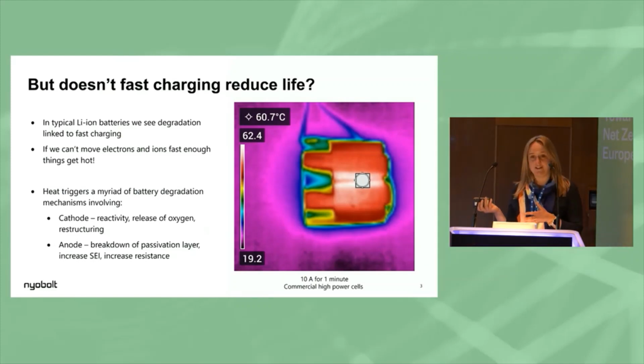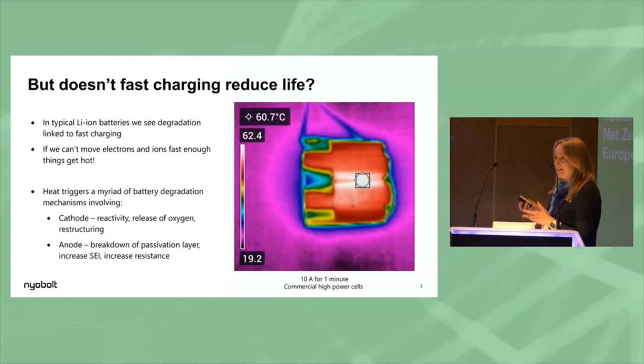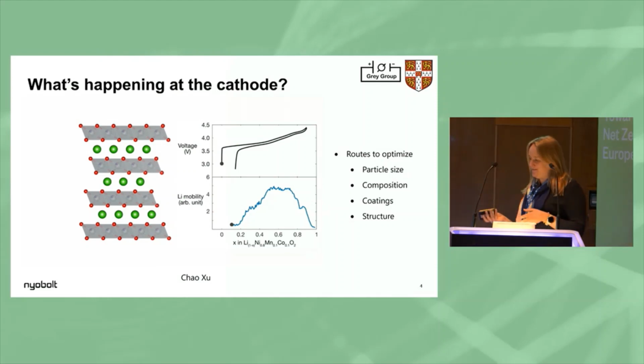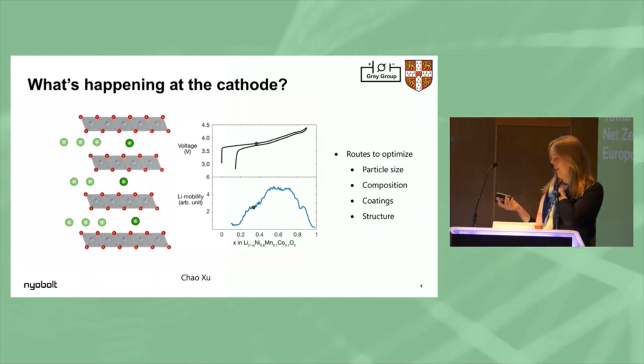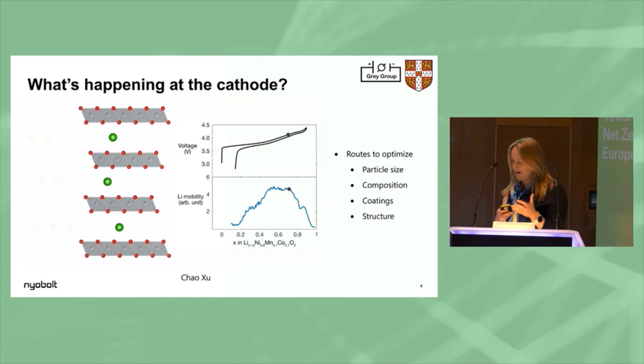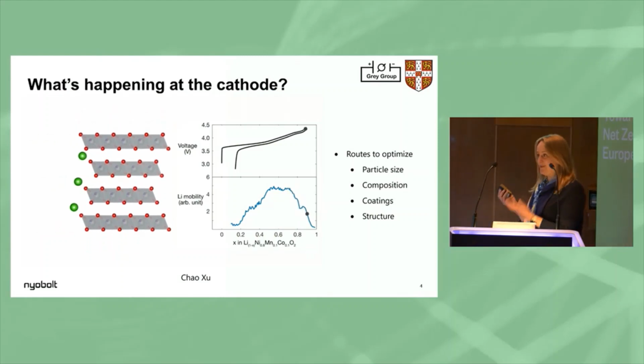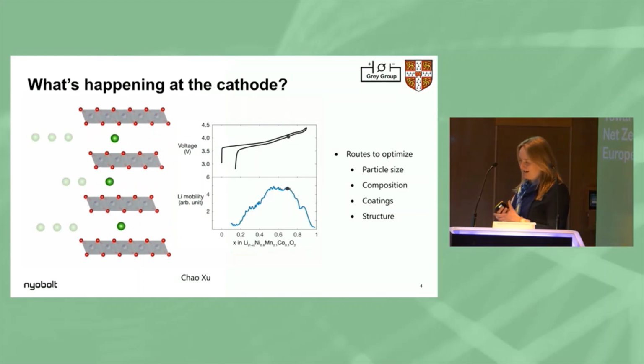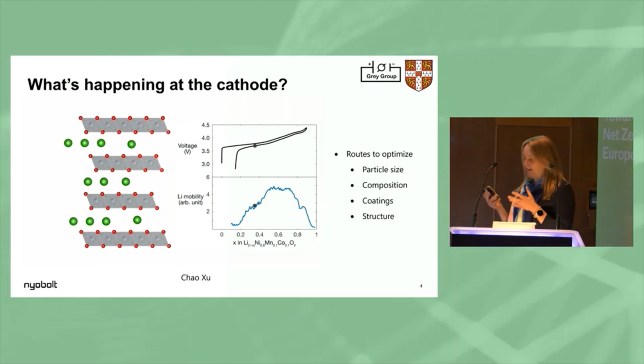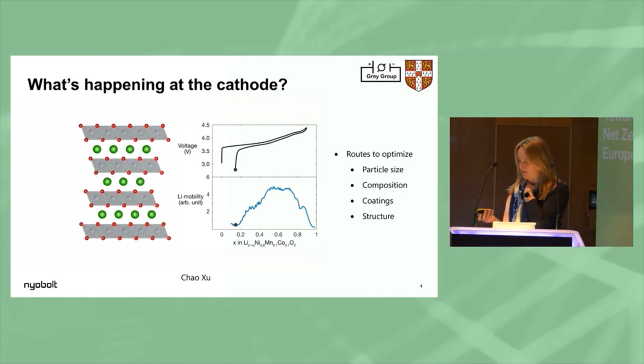So we talked a bit about the cathode this morning. We heard about the cathode reactivity, especially as we're moving to higher nickel materials. And on the anode, we get this breakdown of the passivation layers, increase in the SEI, and an increase in the resistance. So if we think about how we can address this and enable that fast charging, on the cathode side, we had a great discussion this morning. But as we move lithium ions in and out of the cathode, we see this changing in the spacing of the layers. And there are routes to optimize this, some of which we heard this morning. So there's excellent work happening in those areas, around the morphology, around doping, coatings, and the particle size.